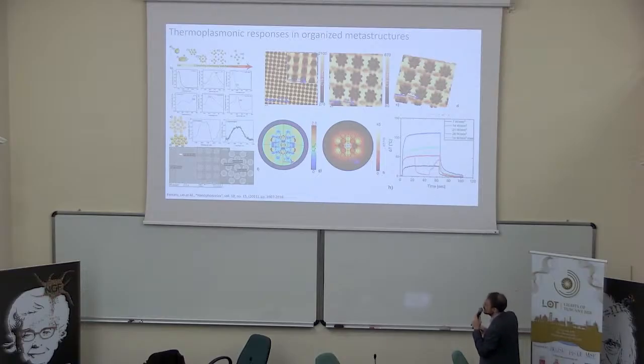It was in an area of more or less a couple of hundred microns, so we utilized the laser beam, we did the experimental measurements, and we saw that these structures are very good to reach high temperature with not so high intensity or power of the laser, and it is almost stable for a time close to a minute.